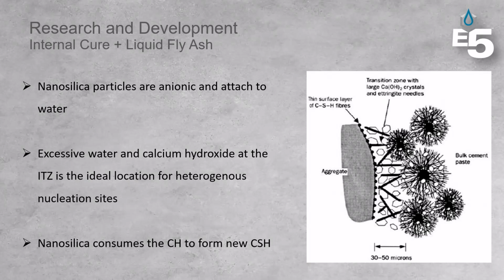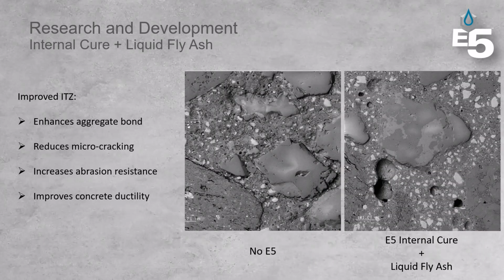When cement gets wet and it's being mixed, it establishes this bulk packing phenomenon that won't let it get in there to the ITZ. Well, nanoparticles are small, and nanosilica is 100 nanometers or less, and it likes water, and it consumes calcium hydroxide to form more calcium silicate hydrate, enhancing the interfacial transition zone. Just the creamy nature alone of the mix that's provided by the E5 internal cure products. You can see on the right how much more cohesive and uniform that bond is of the aggregate to the paste versus the same mix without those products.